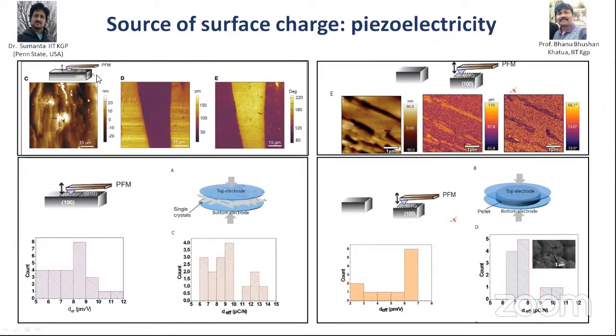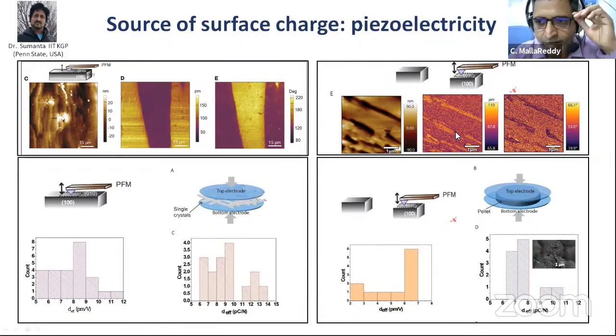So in terms of the deformation, the mechanical stress is being applied along which axis then? That is applied along the 0, 1, 0 axis. So that is the B direction. You're right, we are not applying the stress along the polar direction of the crystal. You're applying somewhat at a 90-degree angle to that. We have not done the measurements on the tip, so that might give us a slightly different piezoelectric response.